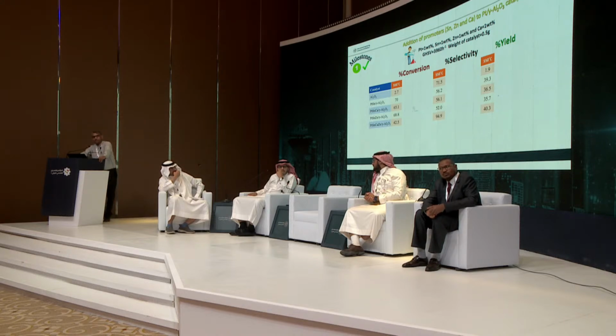Let's talk about the comparative study of the catalyst. On the left side, we are comparing the support, which is gamma alumina, then a platinum-tin catalyst supported on gamma alumina, and then adding promoters, which are calcium, zinc, and calcium and zinc together. Look at the conversions. The initial conversion of the support is very low, whereas the last catalyst, platinum-tin calcium zinc, shows 42.5% conversion.